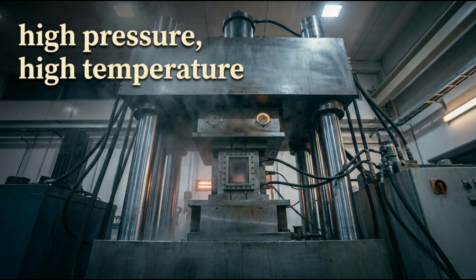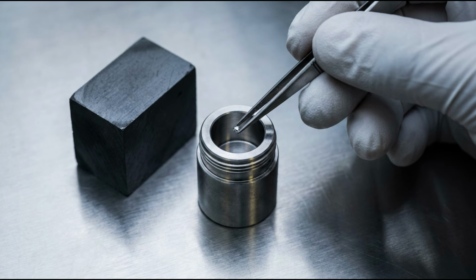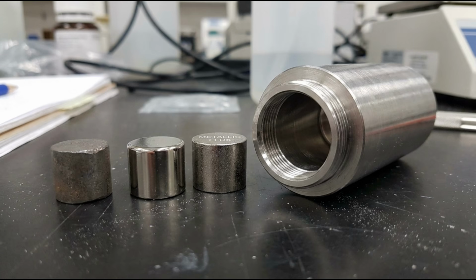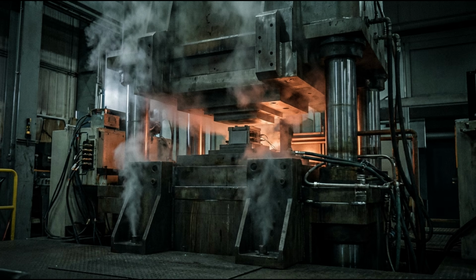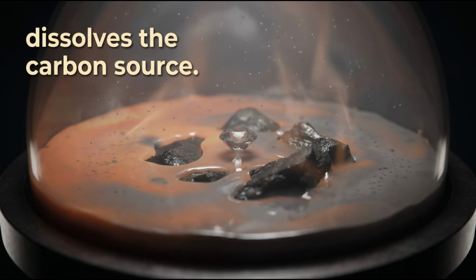HPHT means high pressure, high temperature. A small diamond seed is placed inside a growth capsule with a source of highly purified carbon. The capsule also contains a metallic flux, commonly involving iron, nickel, cobalt, or a combination of metals. A specialized press subjects the assembly to pressure above roughly 870,000 pounds per square inch while raising the temperature to approximately 1,300 to 1,600 degrees Celsius.